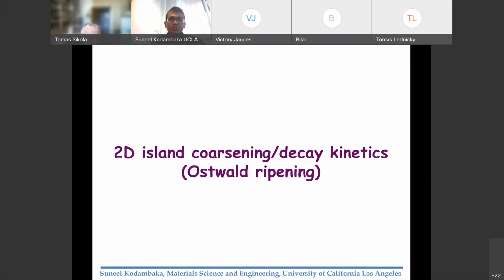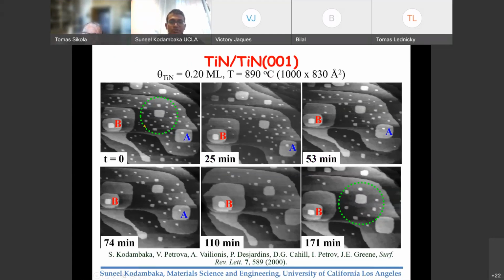Okay, first, let me focus on the phenomenon of Ostwald ripening. And here is a snapshot of similar experiments that were done at slightly about the same temperature, 890 degrees C. And this is as time progresses. Initially, you start out with a large ensemble of islands, 2-dimensional islands. And I should mention that these are all titanium nitride steps. And these steps are single atom height steps and on an otherwise atomically flat terraces. And you see a few large islands and a lot of small islands.